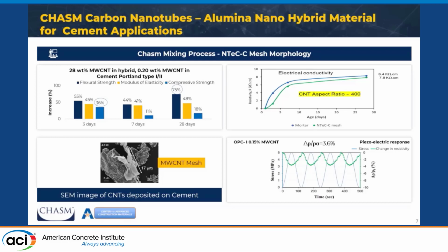Well, in the beginning of this project we prepared different NTEC mesh formulations having different carbon nanotube content in the hybrid material, and we blended with cement particles in different proportions between 0.10 and 0.20%. We shipped this material to Chasm for determining the electromechanical performance, and you can see an excellent performance versus mortar at different aging times. And what is spectacular from this material is the high performance in the early stage.